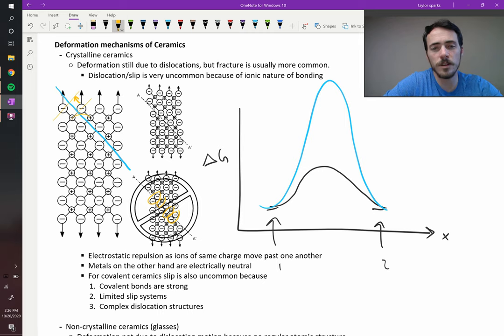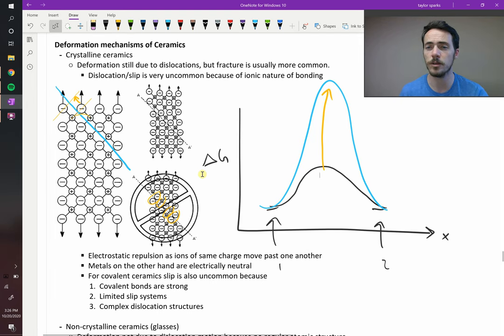That is extremely not favorable because ions of the same charge repel one another. So that's this extra bump in the energy. And so basically it says it's not worth it. It's too energetically expensive for us to come together. So instead, I'm just going to fracture. I'm going to create new surfaces, which also cost energy, but less than what it was costing to get dislocations to slide past each other.